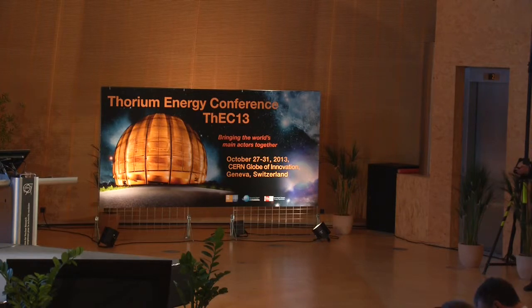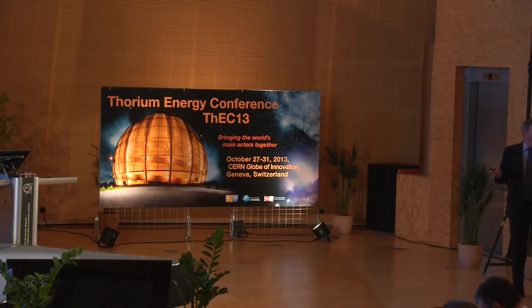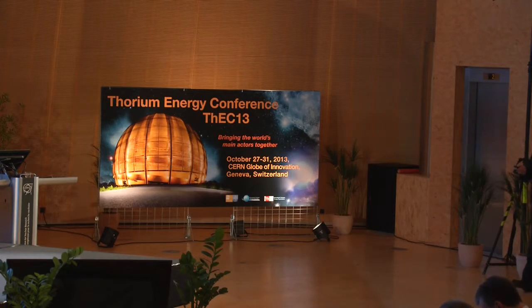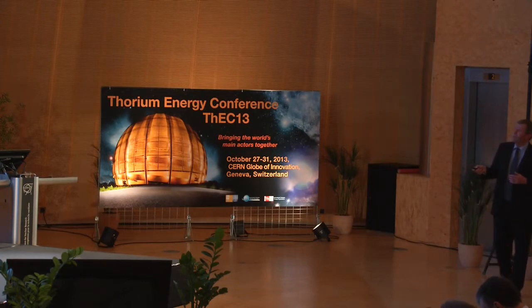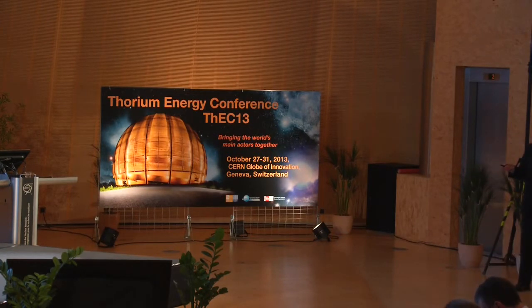And to get properties of those multi-component melts, whether, for example, plutonium would start to plate itself out in the heat exchanger, you need to know about such things for all aspects of the design of the reactor of that level of complexity. So you need to know about multi-component molten salts over a wide range of temperatures, and also for the different compositions, because you're chemically reprocessing all the time, so the composition of the mixtures will be fluctuating as you move along in time. You need properties like the solubilities of these elements, heat capacities, thermal conductivities, and chemical activities. And those databases simply do not exist.